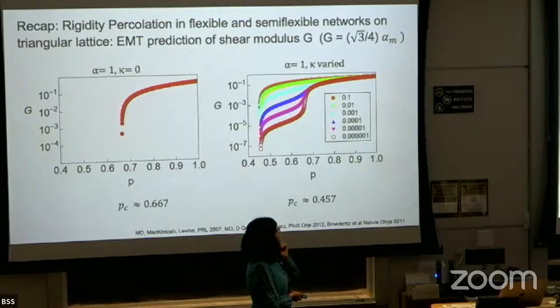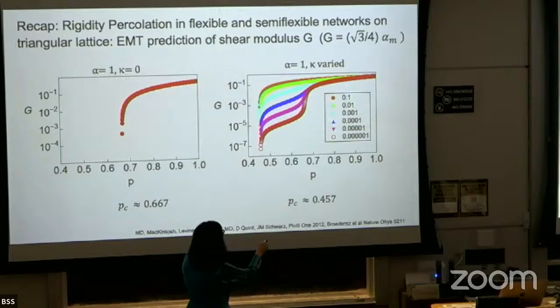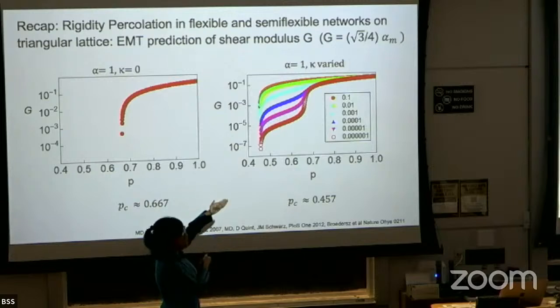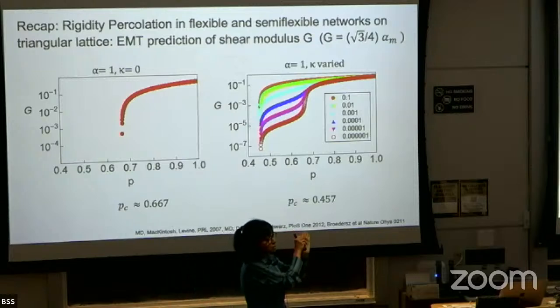But the thing is, even in experiments, let's say experiments are not here or also here. So for actin, this non-dimensionalized ratio is of the order of somewhere 10 to the minus 3 to 10 to the minus 4. So it's this cyan and blue, and if it's closer to the cyan, it's very difficult to see the inflection. There might be, but experiments are also very hard and messy, so you may not exactly see it, even though it's there. But here, I think if you try to calculate the exponents as a function of P minus PC and stayed very close to PC, you will see some things.